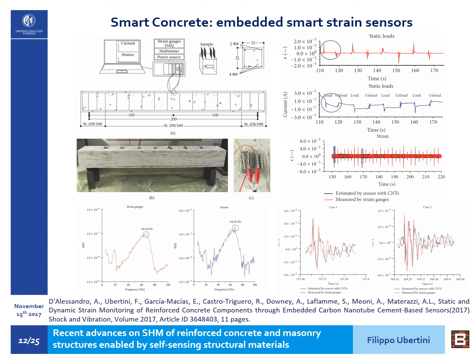So here we see the application of the sensors when embedded into a reinforced concrete beam arranged in the lab. On the top right you see what happens when a person steps over the beam and then steps out from the beam, and this test is repeated 4 times. In red you see the response measured through a strain gauge attached to the cement-based sensors, and in blue you see the response in terms of electrical current of the sensor placed at the mid-span. So clearly you see that with the cement-based sensors you detect the loading and unloading of the beam in a very clear way, and this is valid for all the 4 times that the load is applied to the beam.